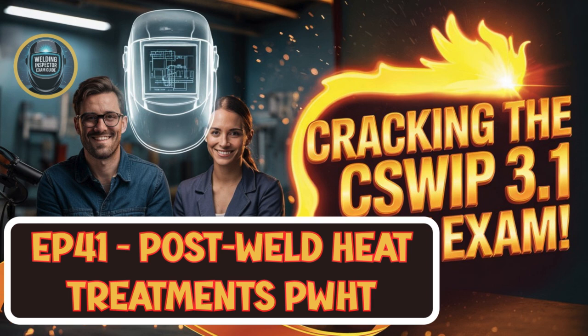Yeah. And this control is especially crucial above around 300 degrees Celsius, maybe 575 Fahrenheit. That's where steel starts to lose a significant chunk of its strength, making it much more prone to distortion if stressed by uneven heating. So how do they track that? With thermocouples, little temperature sensors attached to the surface, placed strategically to represent the thickest and thinnest parts of the item. For typical carbon steels, you're looking at maybe 60 to 200 degrees C per hour heating rate. Depends on the thickness. Slow and steady. Okay, slow heating. What's next?